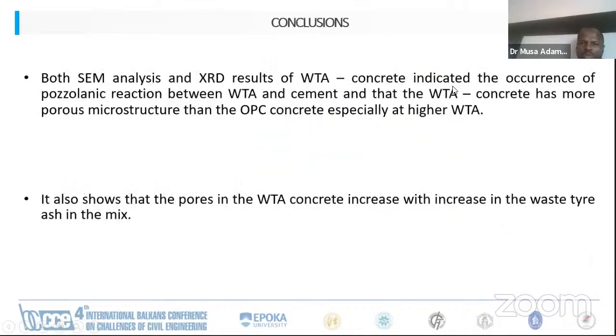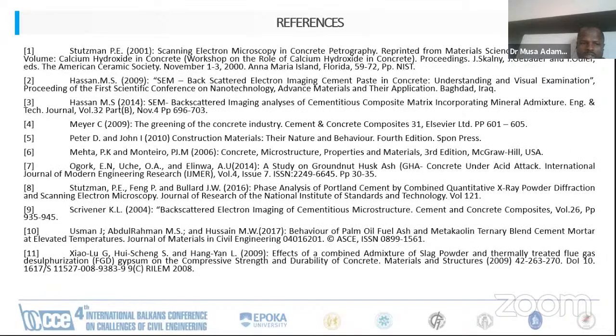So in conclusion, we can say both SEM analysis and XRD results of WTA concrete indicate the occurrence of pozzolanic reaction between waste tire ash and cement, and that the waste tire ash concrete has a more porous microstructure than the OPC concrete, especially at higher WTA. It also showed that the pores in the WTA concrete increase with increase in the waste tire ash in the mixtures. Thank you. These are the references used.